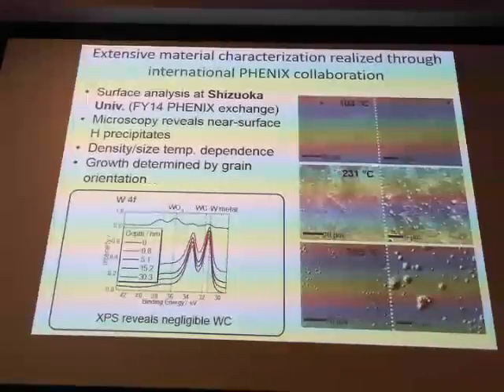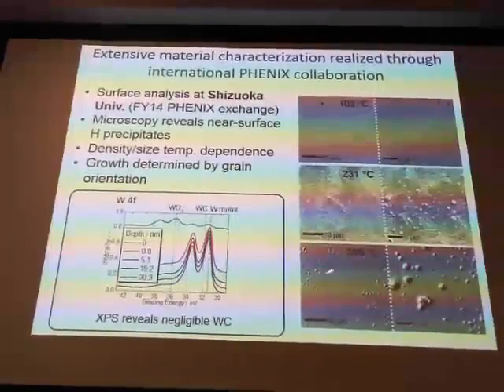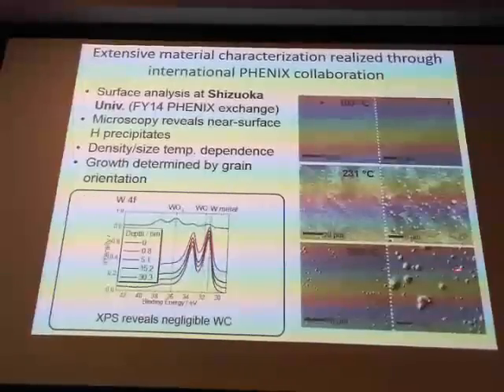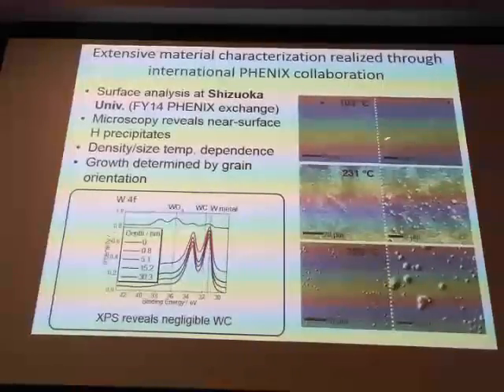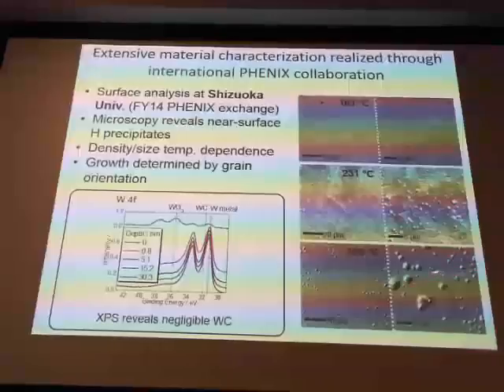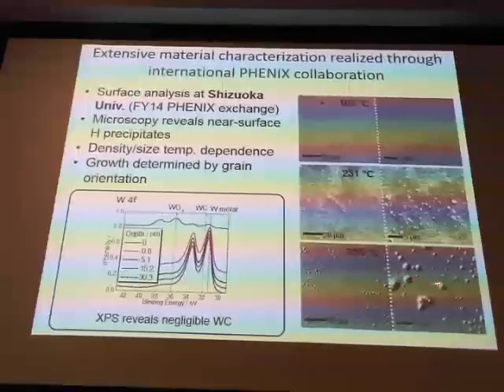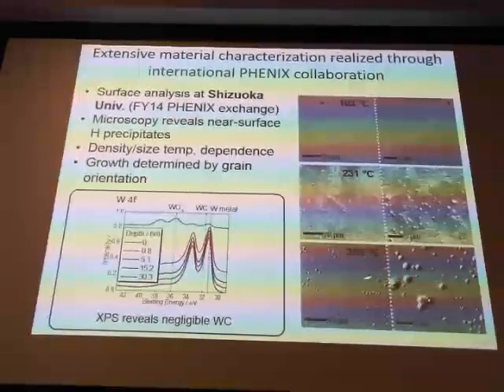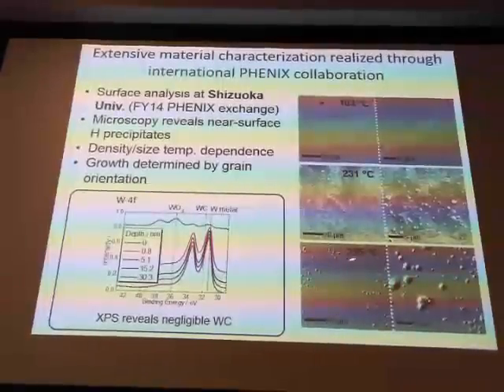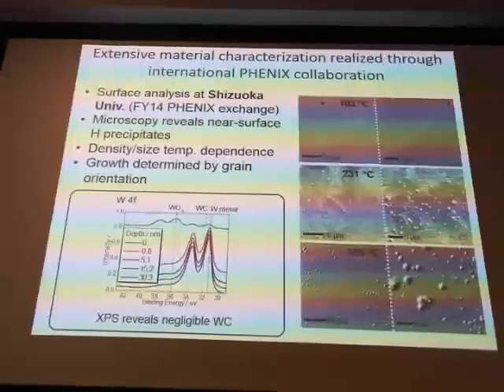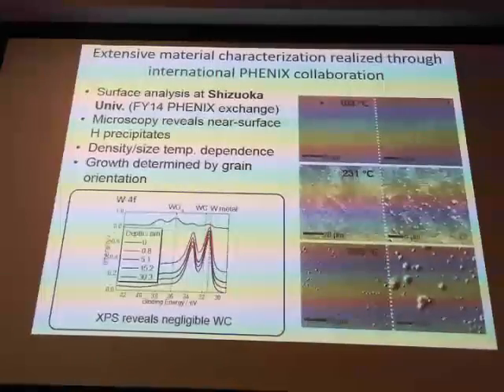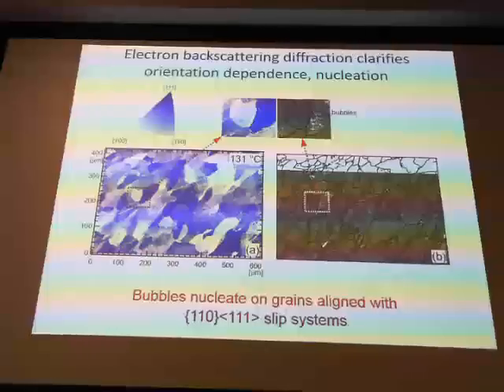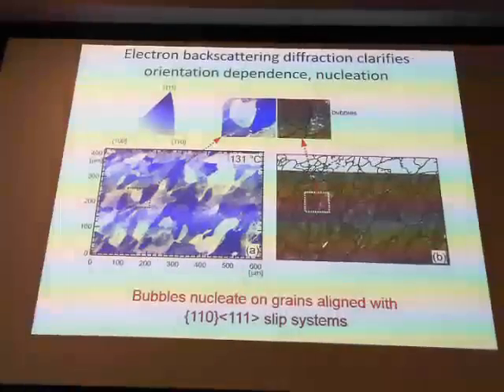Here's an example of 3 different temperatures, and you can see that these are SEM images, different scales, a low resolution on the left and high resolution on the right. You can see the formation of these small bubble networks near the surface as a result. What's interesting is that in this higher temperature case, you see these bubbles on some grains, but not on other grains. And so we did a little bit more detailed investigation of this, did electron backscatter diffraction of the surface, looking at different grain orientations.